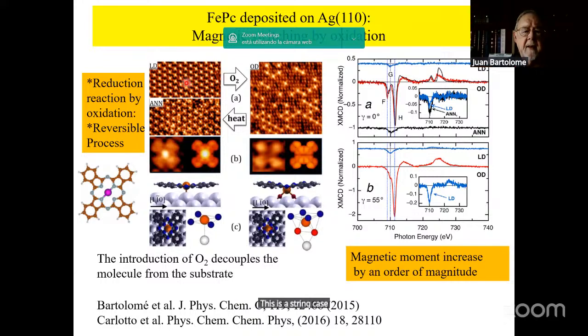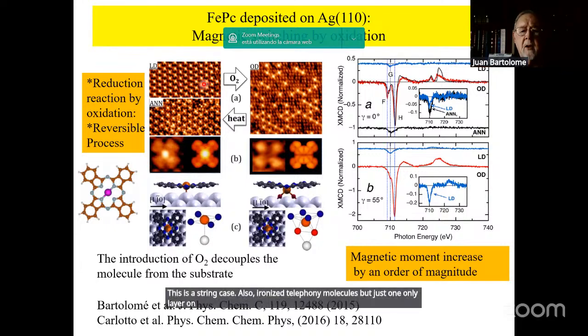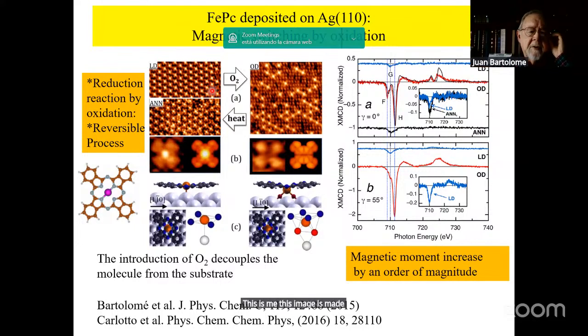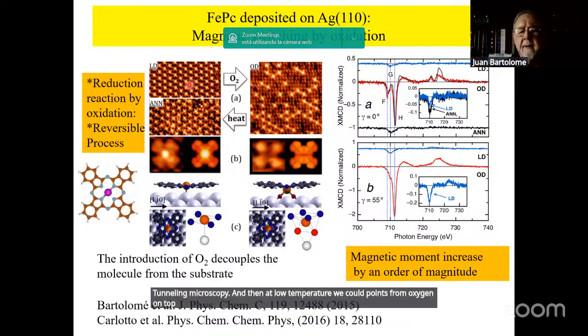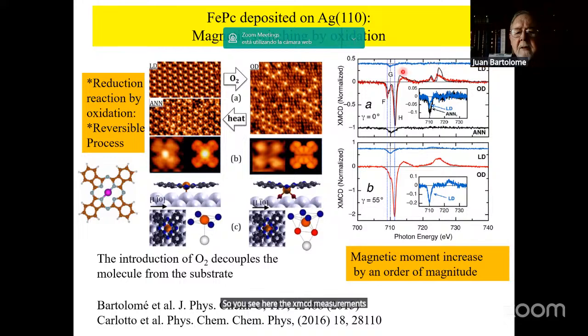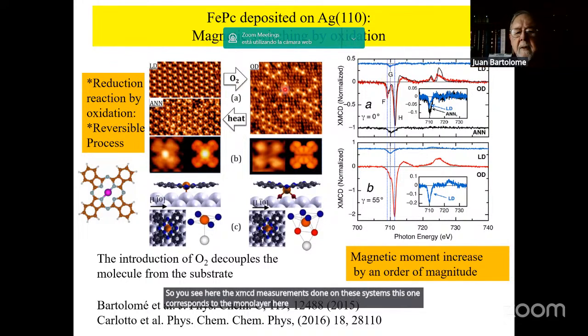Also iron phthalocyanine molecules, but just one single layer on top of silver. This image is made with an STM, scanning tunneling microscopy, and then at low temperature we could put some oxygen on top, and the molecules would reorient and change their electronic state. So you see here the XMCD measurements done on these systems. This one corresponds to the monolayer here, and this one corresponds to the oxidated layer, identical layer.